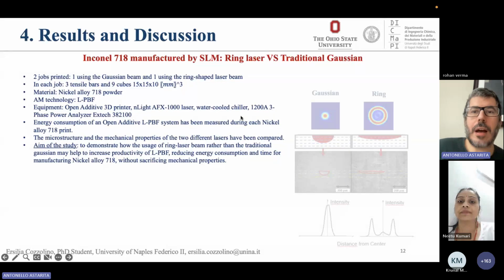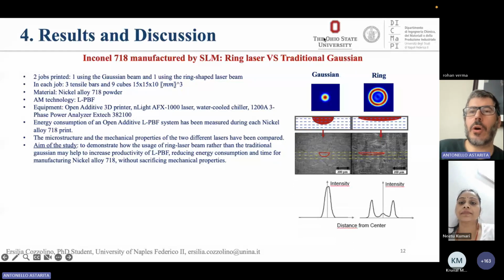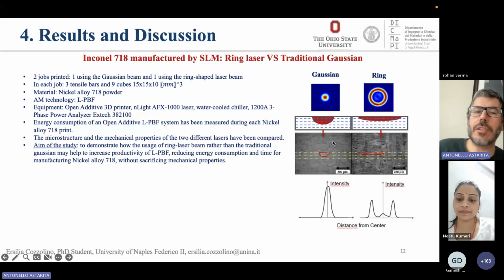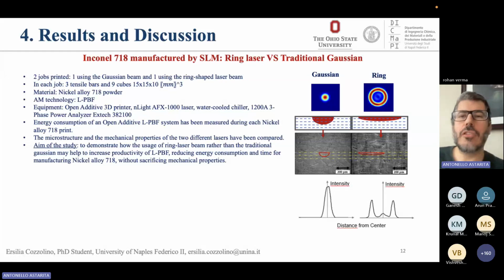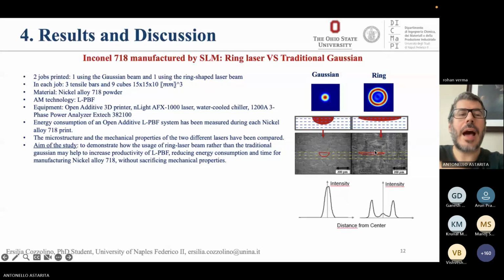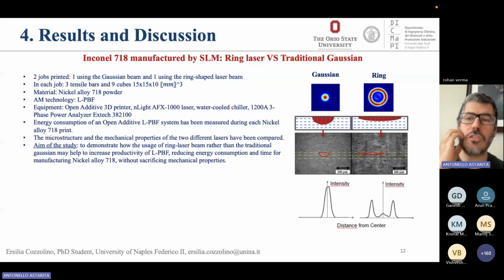Okay. This is a work that we carried out in collaboration with the Ohio State University, trying to reduce. This is a work that has been made by a PhD student of mine, Ersilia Cozzolino, and Ammetti, okay. And in this work, we tried to study the energy consumption related to the use of ring laser. So we, in 3D printing of Inconel, we varied the energy distribution, trying to find out if it's possible, by varying the energy distribution, to find out process condition in which the energy required is lower. Again, if you want to reduce the energy consumption, you have to change the processing condition.